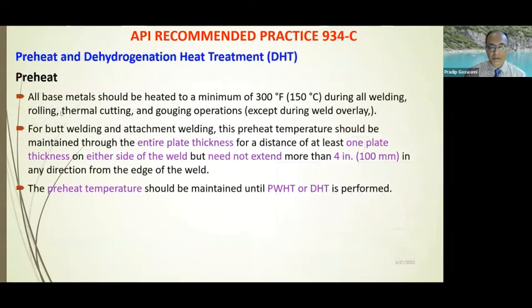Preheat: all base materials shall be preheated to a minimum temperature of 150 degrees centigrade. And this preheat should be a quite wide zone. Basically, it should be something like 100 millimeters in any direction of the weld. The preheat temperature shall be maintained until post-weld heat treatment or DHT is performed.